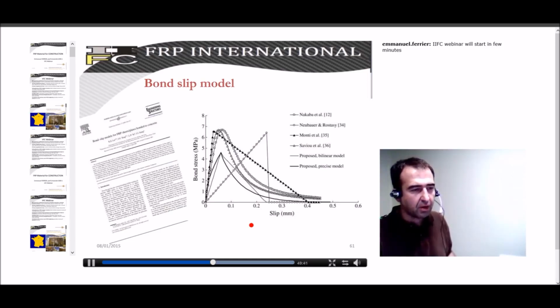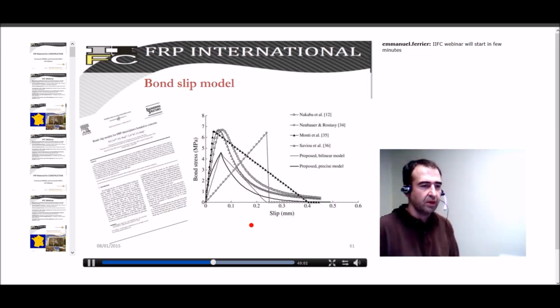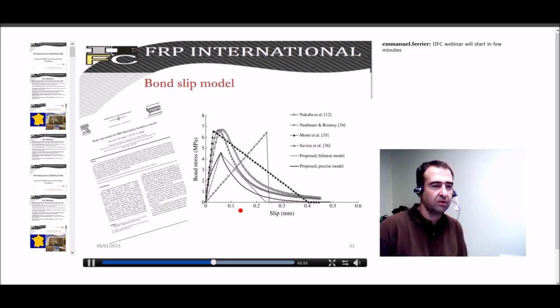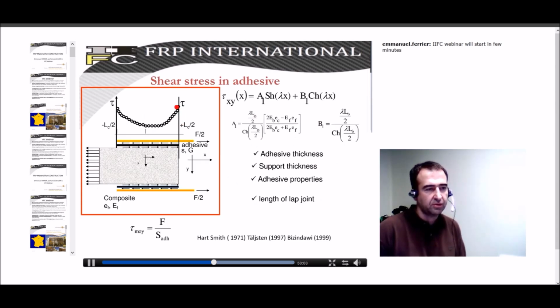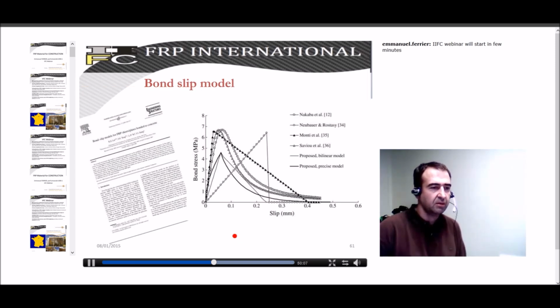More recently, other authors worked on very local bond slip mechanical laws. All those authors have shown that if you focus your study on the peak stress area, you are able, based on the experimental study, to show that the bond stress against the slip can assume this kind of law, a nonlinear law with a decrease which corresponds to the beginning of the debonding. They have identified this kind of mechanical law. Depending on the authors, you will find several proposals.